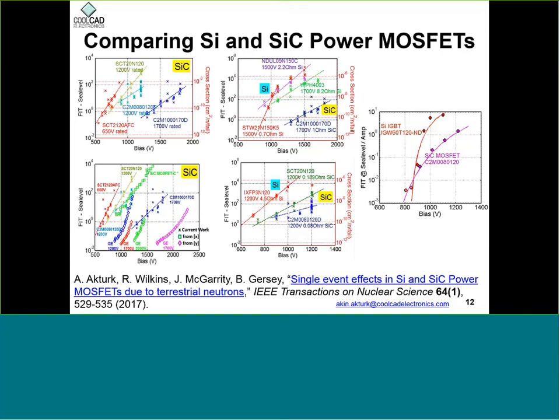And that is true as far as silicon power MOSFETs are concerned, and also silicon IGBTs are concerned. But as you can see on the right, if you go to lower voltages, sometimes there's a crossover point. And at low biases, silicon carbide MOSFETs are slightly more likely to fail compared to silicon power MOSFETs or IGBTs. But as you can see on the y-axis, at this point, the FIT numbers are generally low. And so that turning into a real catastrophic failure event is not very likely, but that also depends on how many of these devices are deployed or used in an application.